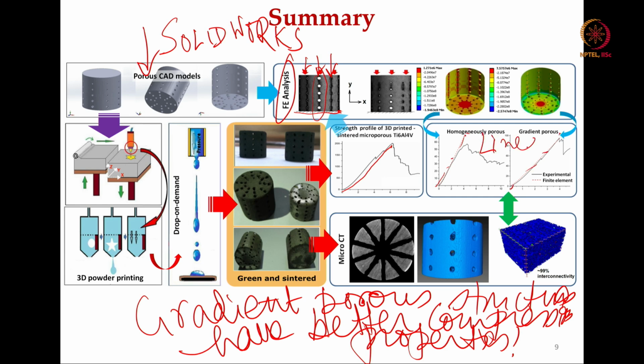In both cases, the linear responses in the FE are very close to the experimentally measured linear response. One of the things that we have learned is that when you use finite element analysis and experiments together, particularly in the context of metal 3D printing, one must use the final component structure after the 3D printing and post processing is over as an input to the finite element model, and certainly not the initial component design which you have produced in the CAD models on the SolidWorks platform or similar platform.